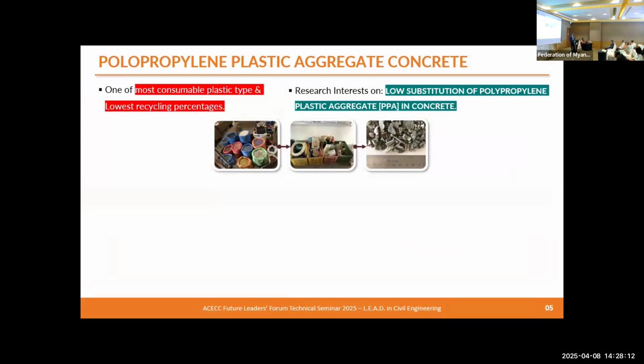When it comes to our study, we did it for a plastic sample we got from the Kandy Municipal Waste Council Plastic and Polythene Recycling Center. When doing the study, we understood that polypropylene is the most common plastic waste available there, and the least recycled plastic waste on the other hand. So we chose that as our plastic type. We are aiming at low substitution of polypropylene plastic aggregate in concrete.